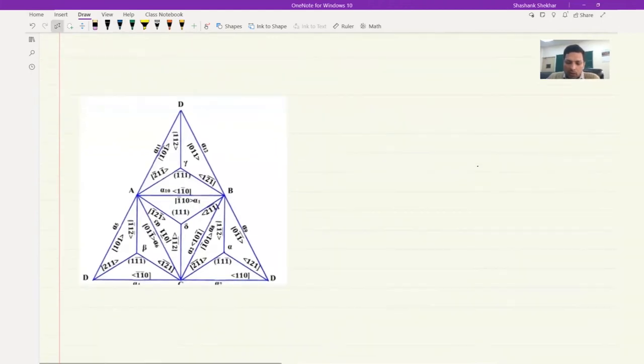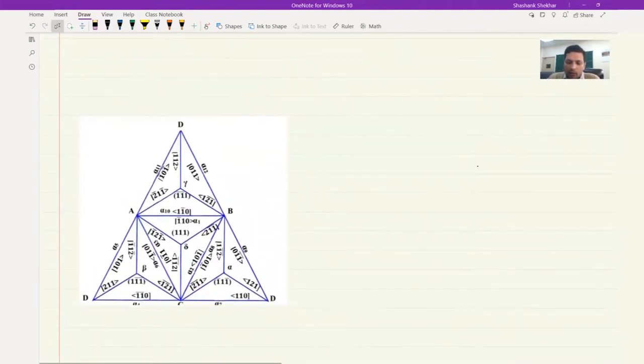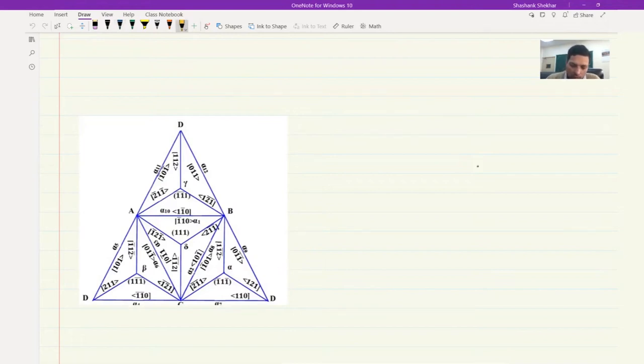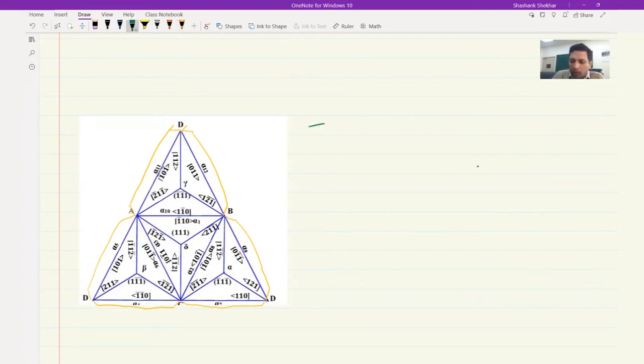If you do a simple search on Google, you would be able to find some images of this. Although I said tetrahedron, what we are looking at here is a triangle — it is because it is drawn in 2D. If you join D with D and cut along these lines, this will ensure that you are able to fold it. This is Thompson's tetrahedron, which is a very, very powerful technique to identify the planes and directions in FCC systems.